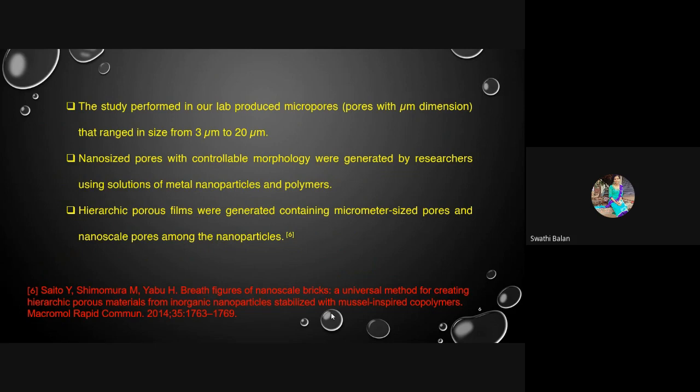And the study which is performed in our lab produced micropores which ranged in size from 3 micrometer to 20 micrometer. Nano-sized pores with controllable morphology were generated by researchers using solutions of metal nanoparticles and polymers, which produced hierarchic porous films containing micrometer-sized pores and nanoscale pores among the nanoparticles.